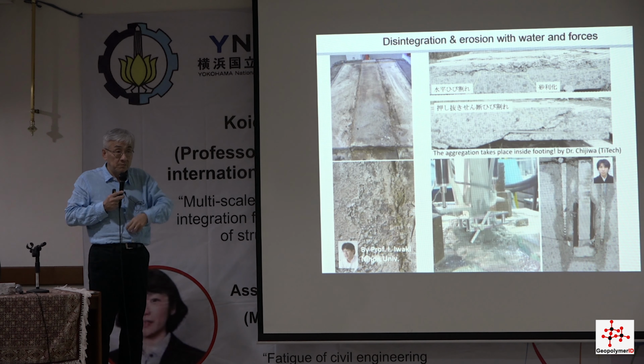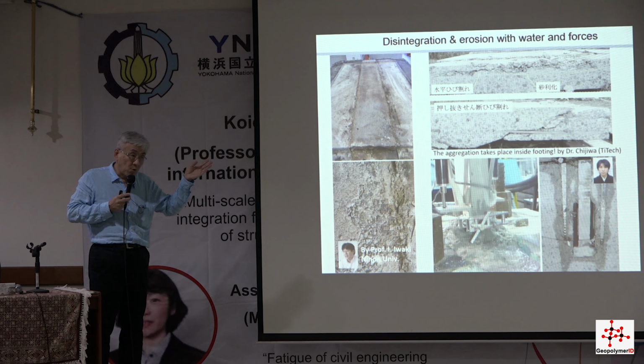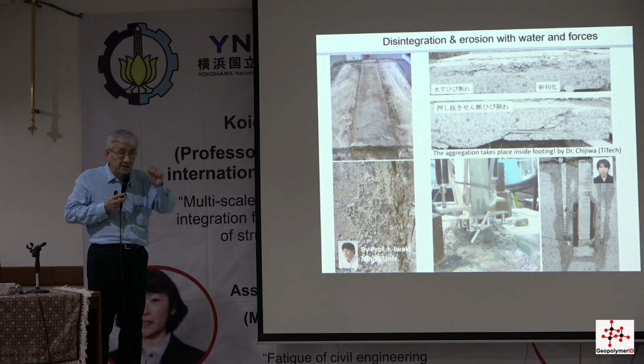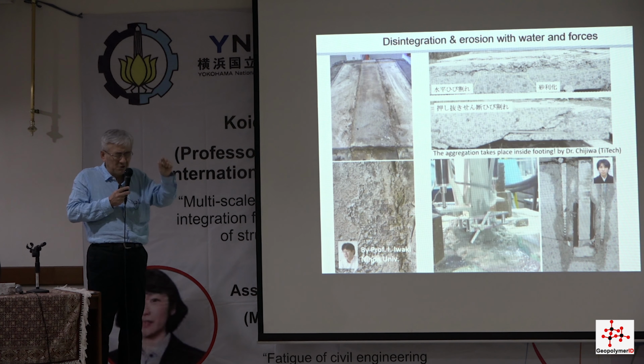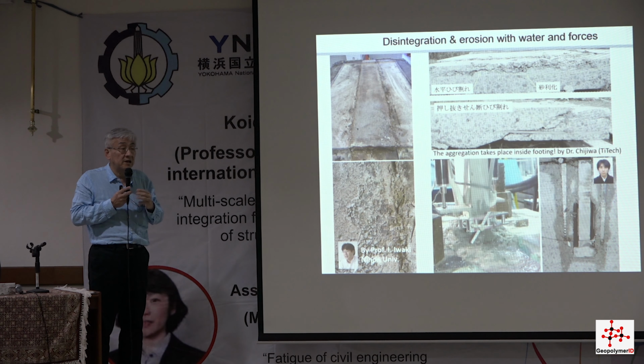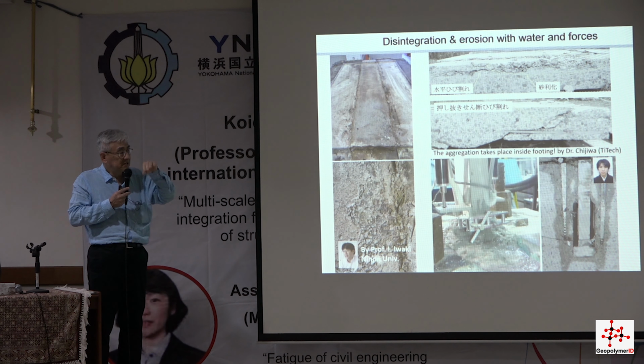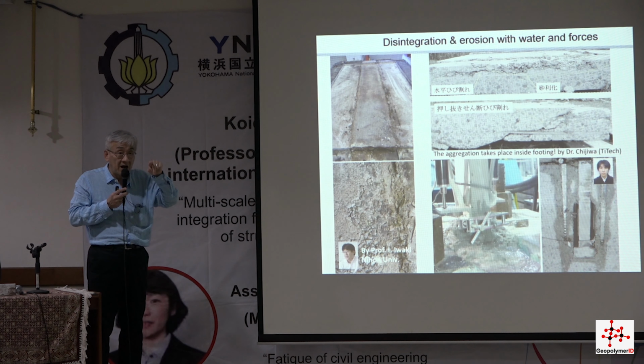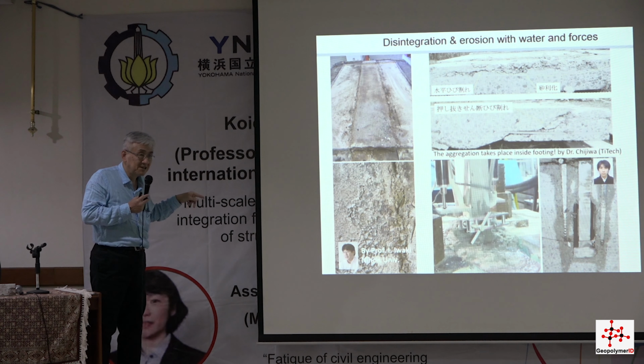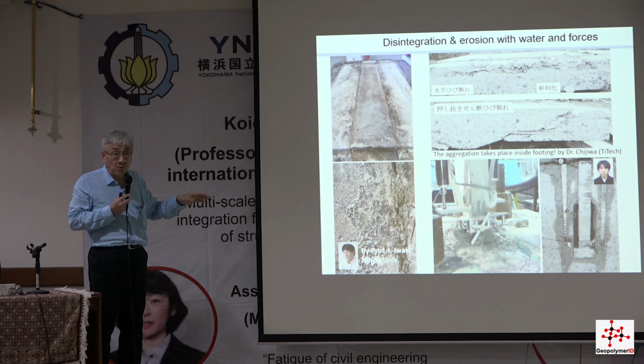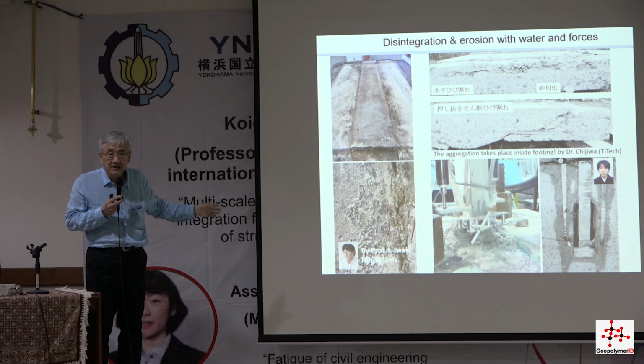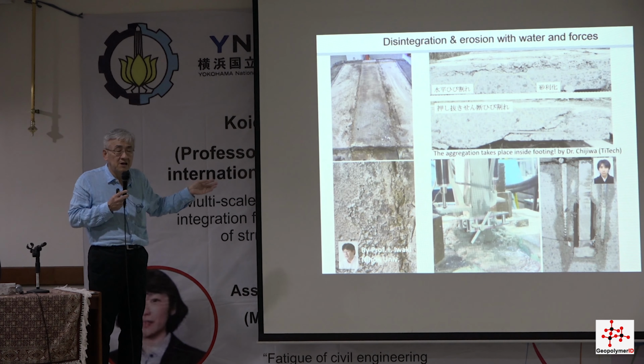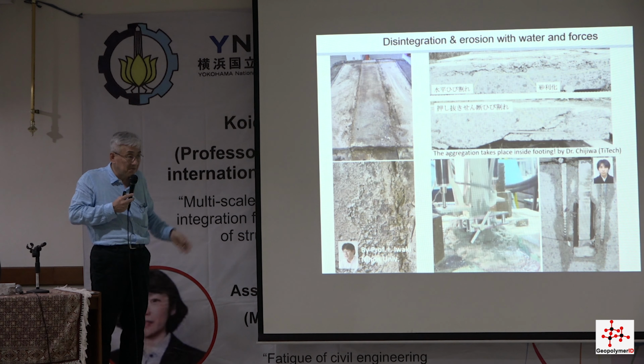Therefore, when we have pressure rise inside this concrete, this pressure can come to the capillary pores. But you know that the capillary pores are microscopic, micrometer size. Always these capillary pores are around the interface zones between the surface of the aggregate and cement paste. Therefore, very big cyclic water pressure comes around the aggregates. Therefore, when we use this type of concrete, if you encounter this problem, how do we solve these problems?